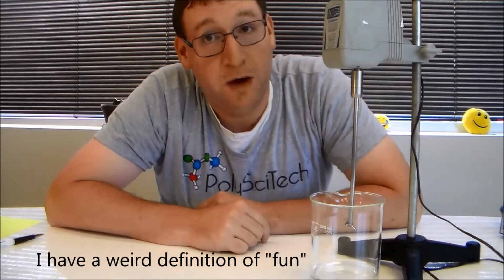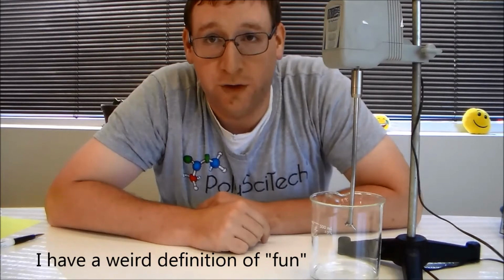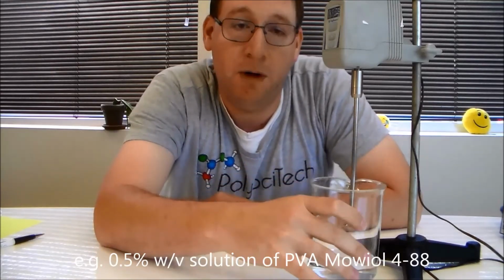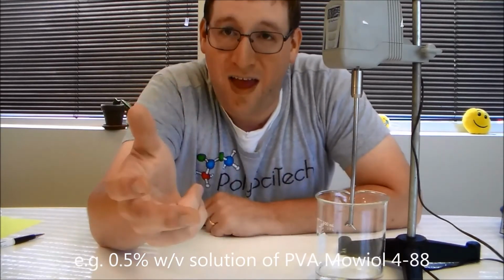There are many processes for making microparticles. Obviously, one of them is not simply cutting it down to micron size with a knife, although that would be fun. That's not typically the way they are generated. Most common is the emulsion technique for generating microparticles. This technique is done by essentially taking an aqueous solution, usually of a surfactant, polyvinyl alcohol for example, or some other material which can create a micelle. We covered micelles in a prior video. Taking the solution, that surfactant, mixing it in with water, and stirring it overhead.